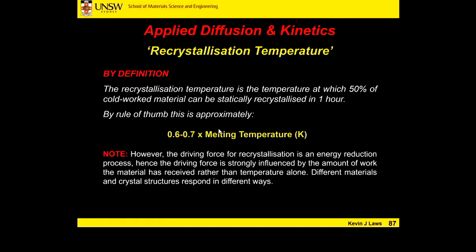But down here, this is our note. However, the driving force for recrystallization is an energy reduction process. Hence the driving force is strongly influenced by the amount of work the material has received rather than the temperature alone. Different materials and crystal structures respond in different ways, so there's this codependence. If you've only deformed your material a little bit, there are fewer nucleation sites for recrystallization to occur, and we'll get onto the sites themselves in a moment. Which means you might have to choose a higher recrystallization temperature to get things moving, or sit it at a temperature for a longer period of time.